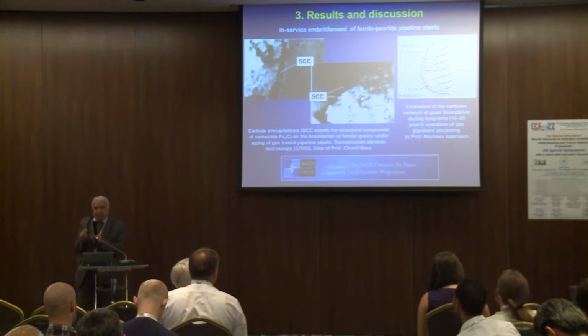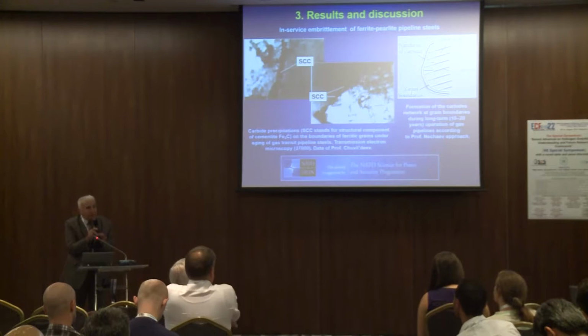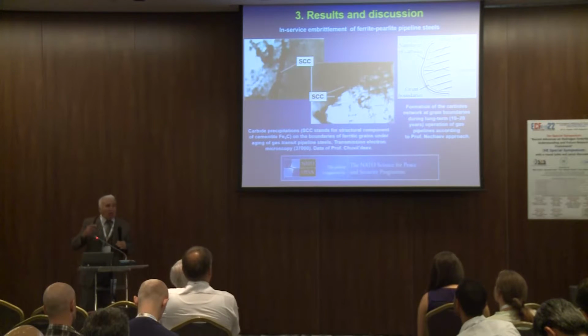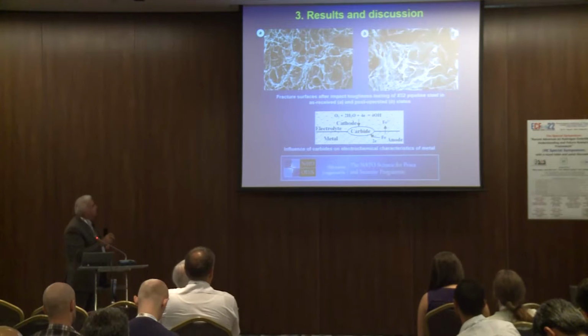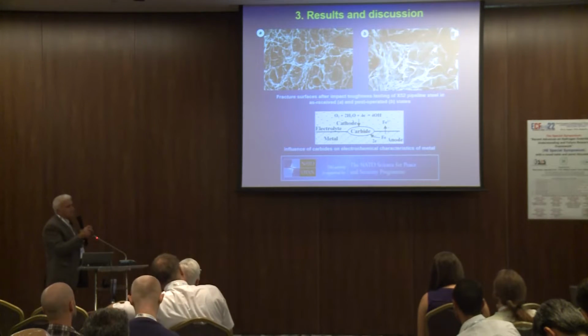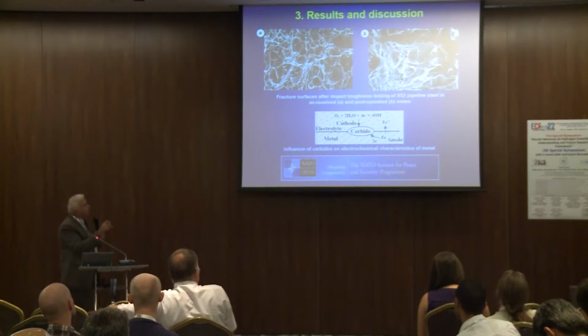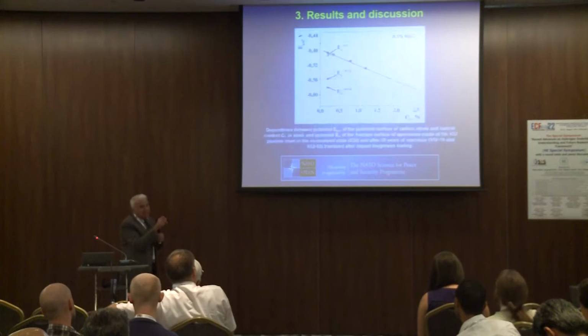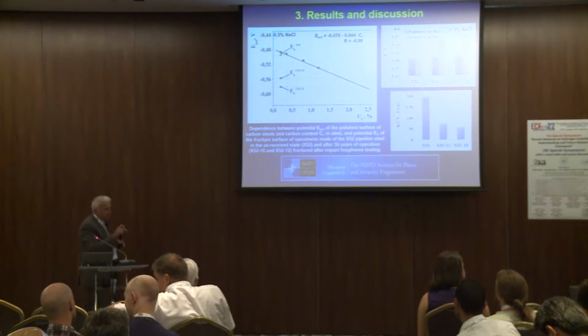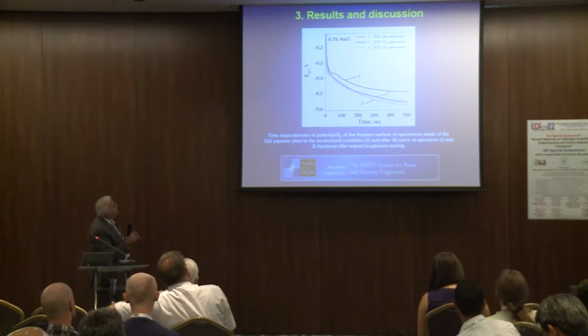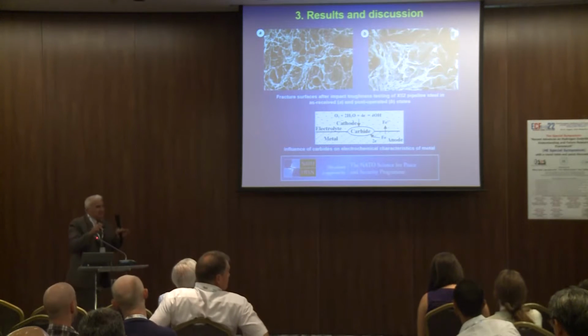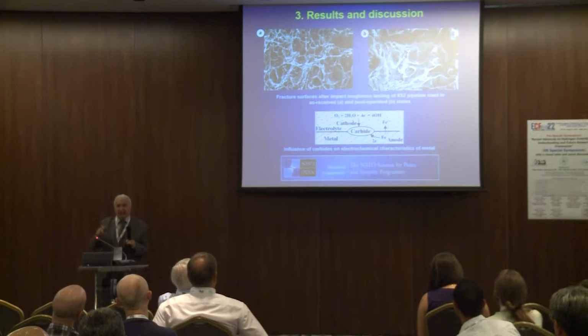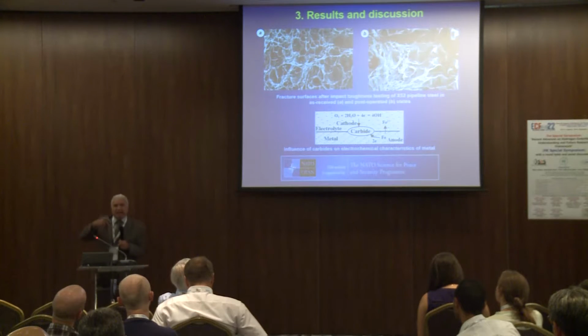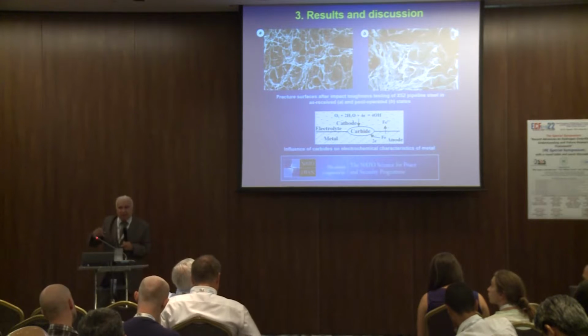We suppose the same process can occur inside the grain, if only 1 micron is enough for formation of carbide, which causes brittle fracture, and in such a way to explain also transgranular brittle fracture during service. On the left, you can see the ductile behavior of metal in the as-received state, and on the right, after operation, you have typical transgranular brittle fracture. But in our opinion, this brittle fracture behavior is caused by enrichment of the fracture surface by carbides. It means the surface is enriched by carbon, by carbides.